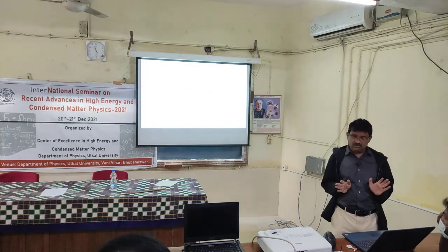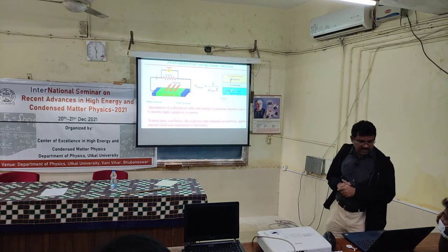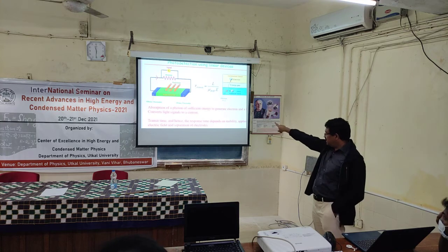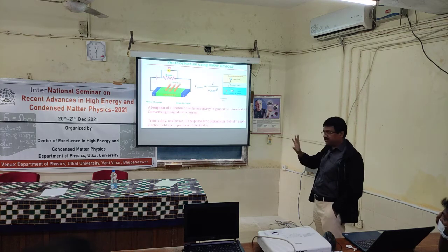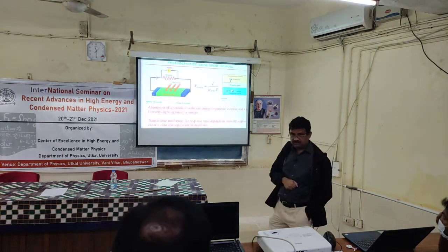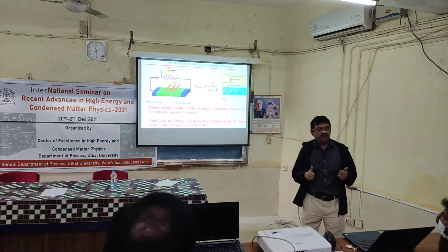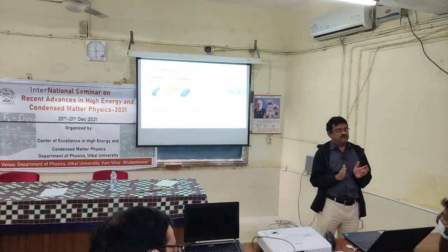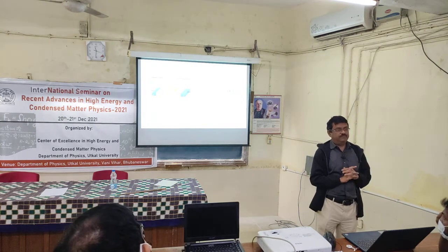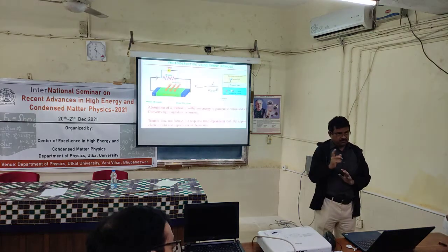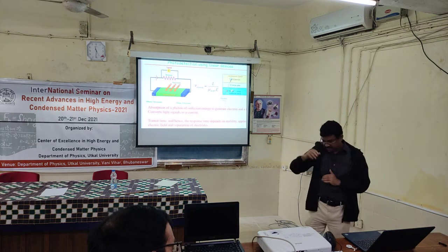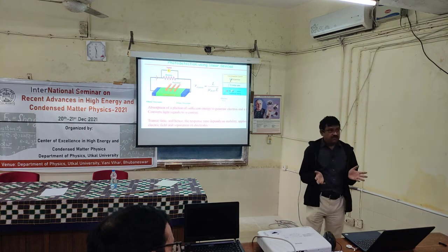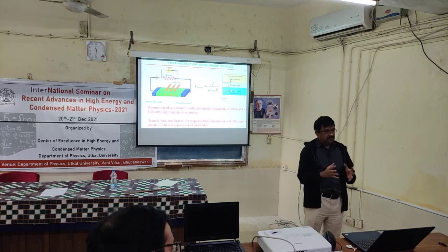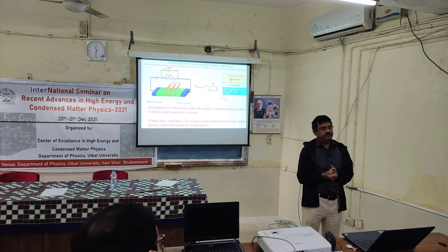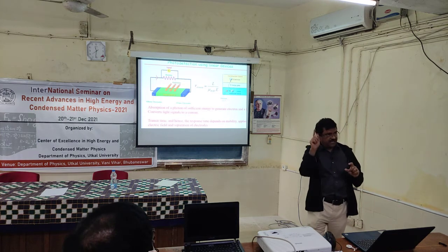I get diode characteristics, and that can be used. Each one has some advantages and disadvantages. The linear device is very simple. The principle is as you see here. There are ohmic electrodes, that is metal, on this side, and on this side also ohmic electrodes, that is also metal. In between we have the semiconductor. Now when you shine light, you generate electron hole pairs depending on the wavelength of the light and the band gap of the material. Lead sulfide has a band gap of 0.4 electron volt, so it can be used in the NIR or infrared region. If it is zinc oxide, the band gap is 3.2 electron volt, which is in the UV region, so it can be used for UV detection. So the band gap should be smaller than the photon energy of the light which I am irradiating.